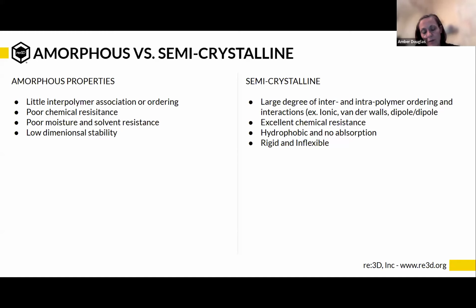Whereas semicrystalline polymers have really good mechanical properties, and that's to do with the crystalline bonds they have there. To break that down, you would have to have really strong chemicals to dissolve any sort of crystalline polymer. And even still, you have to have really high temperatures when you're putting a solvent in to dissolve it. So it's really good with chemicals. It's hydrophobic for the most part, unless they add some sort of functionality that increases its hydrophilicity. And for the most part, they're pretty rigid and inflexible, unless you add some sort of flexible additive in there to space out the crystalline structure.